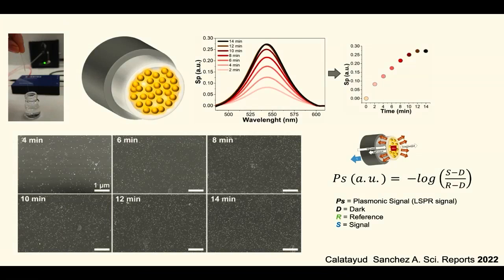Okay, so the next thing is, we can have the spectra. In this case, they were 40 nanometer gold nanoparticles, and we were getting very nicely the plasmon peak of the gold nanoparticles. I didn't add it here, but we did it already: if we add different types of gold nanoparticles, we see all the peaks of the different types of particles. For example, if we add stars that have a plasmon peak around 600, we can see the two peaks. So this is also a very nice way for multiplexing.